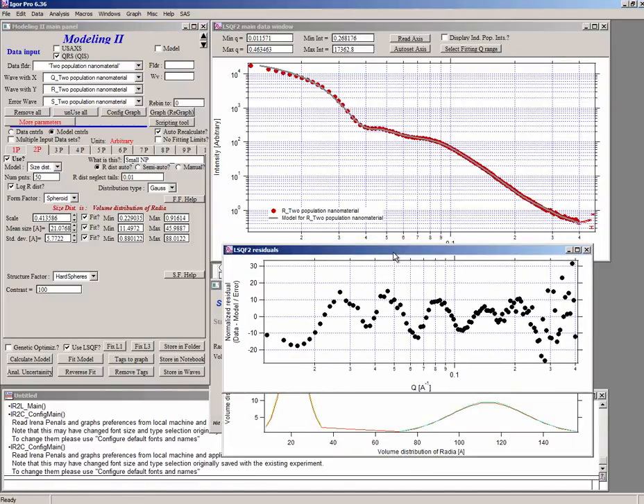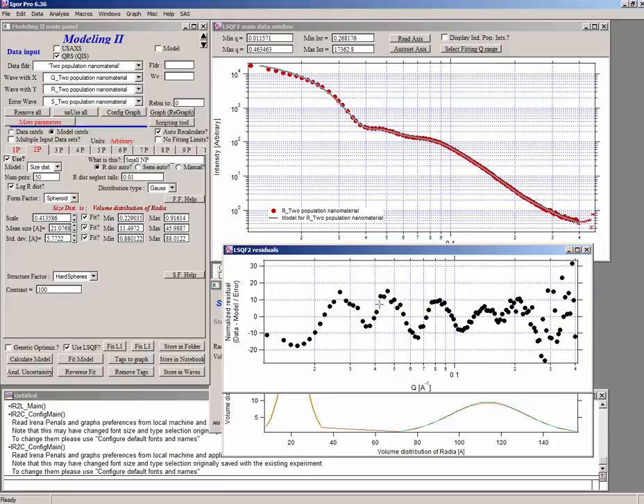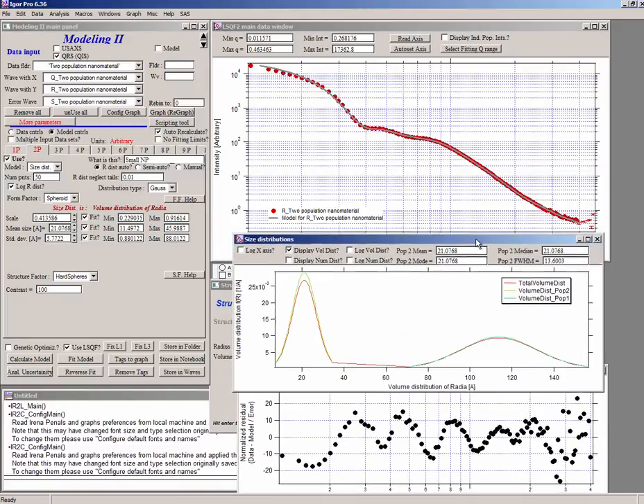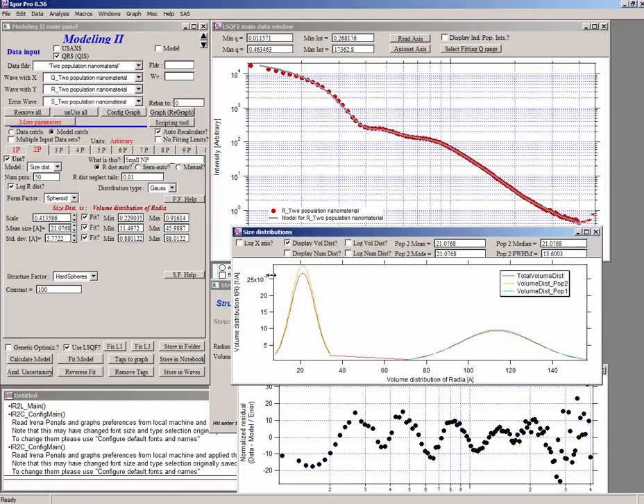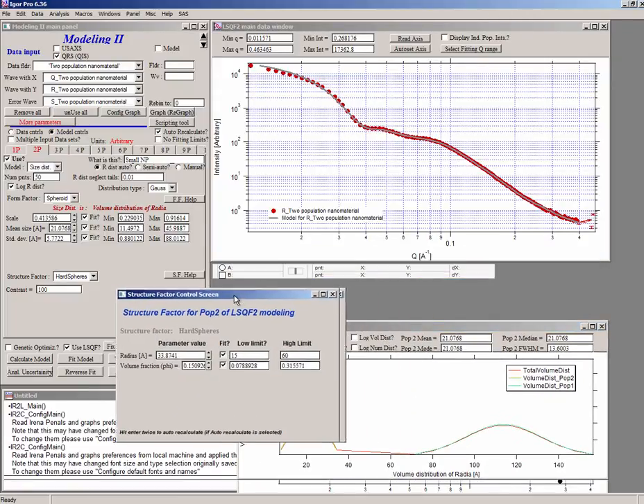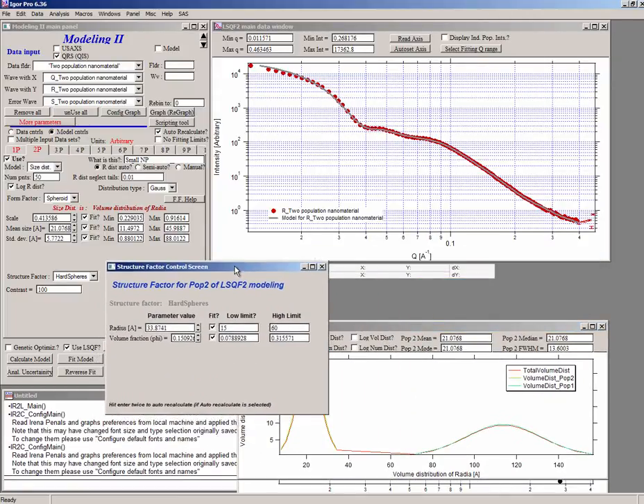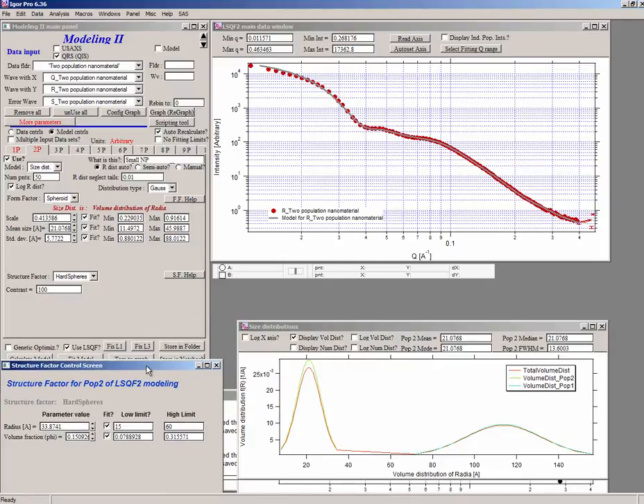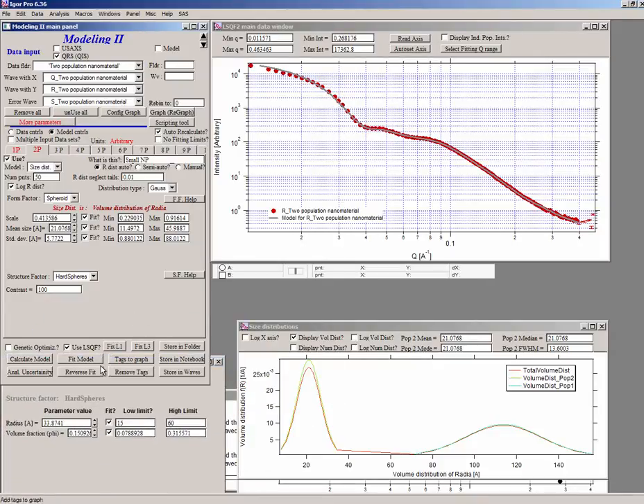Here is a plot of normalized residuals. It's not perfect, but at least it's randomly distributed around the curve. So there's some oscillations up and down, but we're not misfitting systematically low angle or high angle. We have a plot of populations. So we have one population around 20 angstrom, slightly more than that. We have broader population out here, but because it's also much larger, this one produces the Bessel function oscillation. This one does not. And these are the parameters for the structure factor itself.